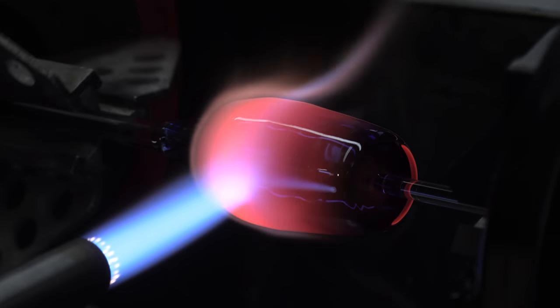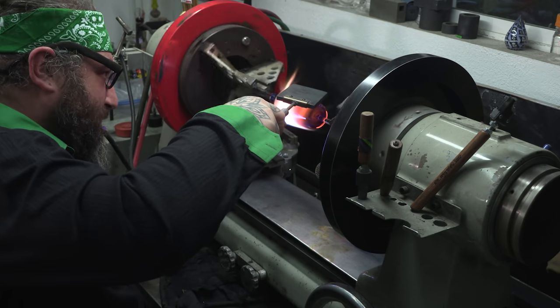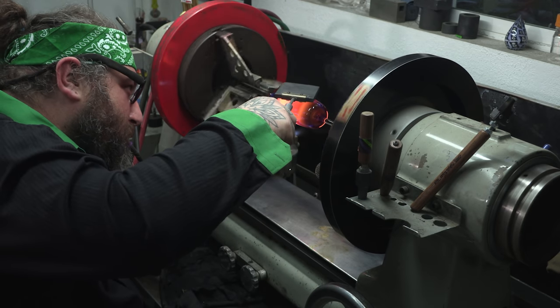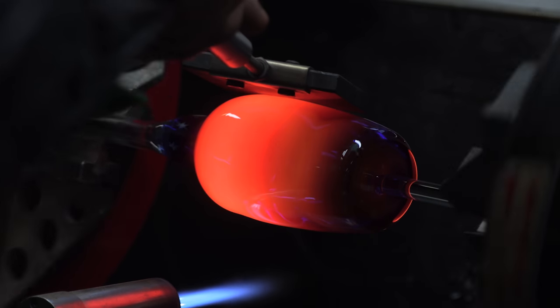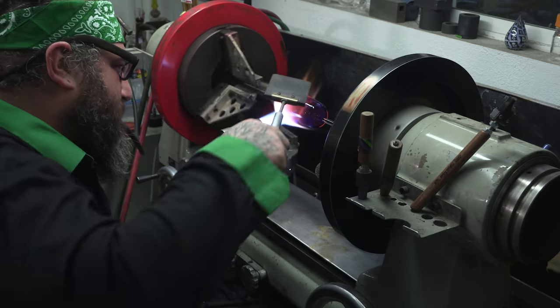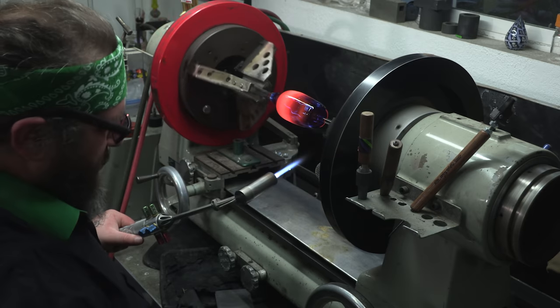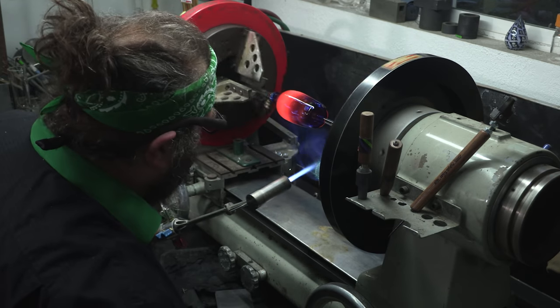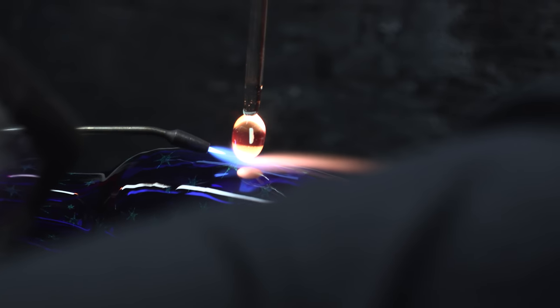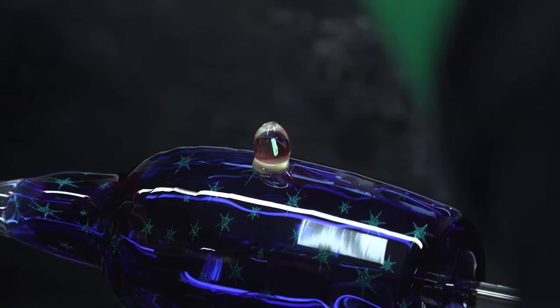Now that you have that crack sealed, going back to shaping it. Make sure the shaping is back where you want it — the whole piece flows as originally intended. This one definitely cracked a lot. It was an unusually high cracking piece, but we still wanted to leave this in the video for you guys to see kind of how to mess with something that's giving you a hard time. It's good to be able to save something like this, especially if you've bought a nice chunk of tube and worked it all day — you don't want to lose it. One thing that's a little tougher on a vac stack or something where there's clear is that the clear can slide into the crack and then you'll see that hole. But if you're using solid color, when they crack they just color — it heals up and looks the same because it is the same. Nothing to flow into that little crevice.